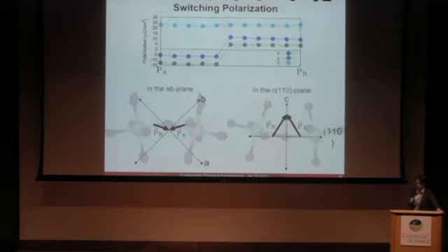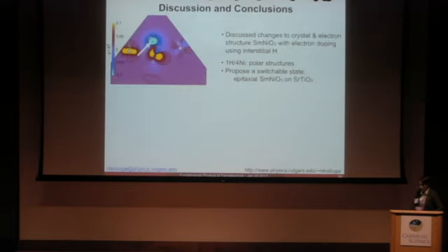So finally coming to the polarization, because the position of the hydrogen doesn't change, the direction of the polarization along this c-axis is relatively constant. However, in the 110 direction, it does flip. So we end up with a switchable polarization of about 23 microcoulombs per centimeter squared.